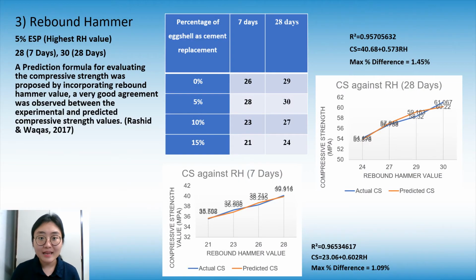For the rebound hammer test, the data had been tabulated for 7 and 28 days water curing. By using the regression method, R-square value had been obtained for the compressive strength value against the rebound hammer value. The graph showed the actual compressive strength and the predicted compressive strength value. It was clearly shown that the R-square obtained for 7 days was 0.965 and for 28 days was 0.957. This means that the rebound hammer has a strong correlation with the compressive strength value. The maximum percentage difference was only about 1%, which is just a small difference from the predicted compressive strength.